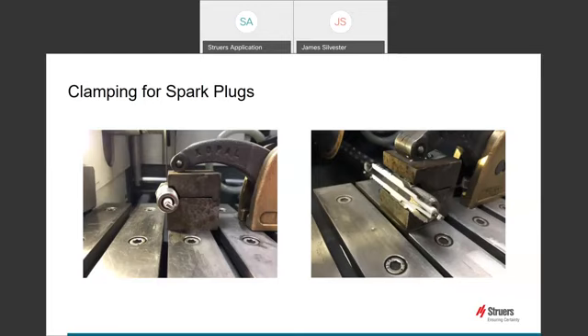Precision is key when carrying out such a cut, and so the precision saw was used due to the thickness of the blade, allowing us to position the clamp very close to the cutting axis. The complexity in this case is amplified by the variety of materials in the spark plug, with metal and ceramic being in the same part. We use the diamond blade for this part because the ceramic part would be just too hard for a standard abrasive wheel. It is important to note that when using diamond blades, we use the stay function when cutting to prevent potential damage to the diamond abrasive when retracting the wheel.